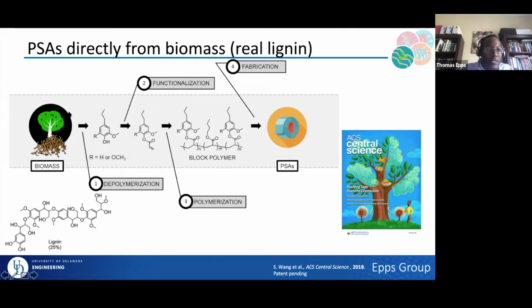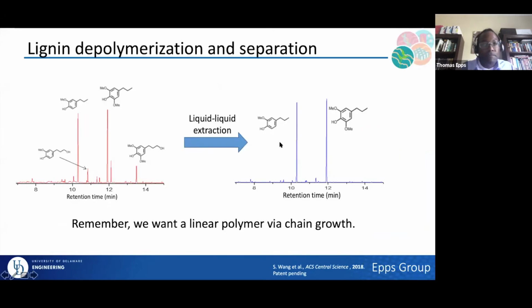So one of the things I'll mention is that poplar wood looked basically like sort of brown sawdust. We actually used an old burr grinder, about a $20 to $40 burr grinder, and ground it up so that we could do the depolymerization. We did a catalytic depolymerization. If in the Q&A, I'm happy to talk a little bit about the work we've been doing there on optimizing that. Then we functionalized it, made the block copolymer, and then tested.